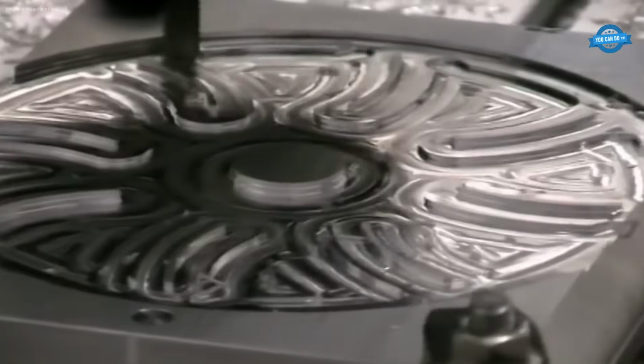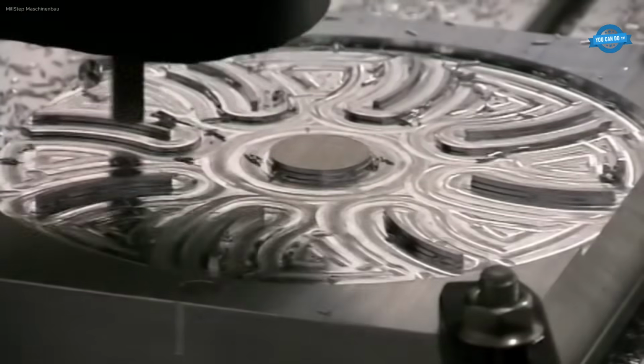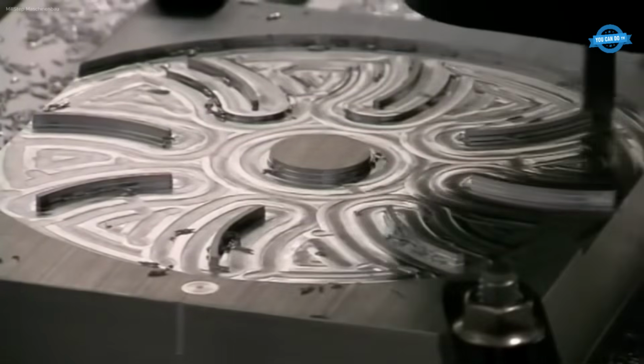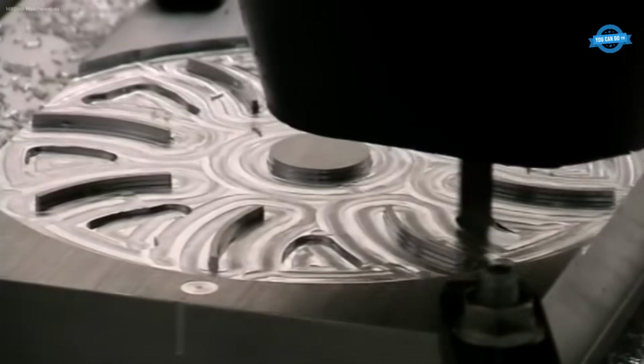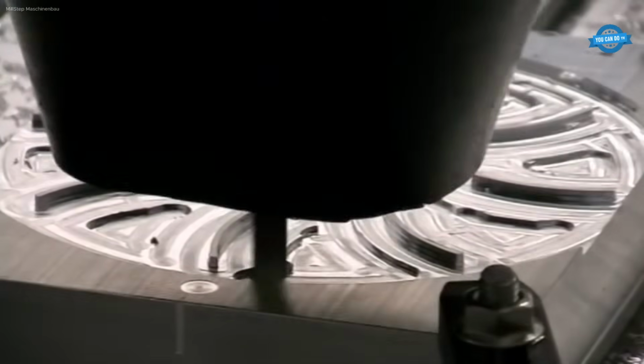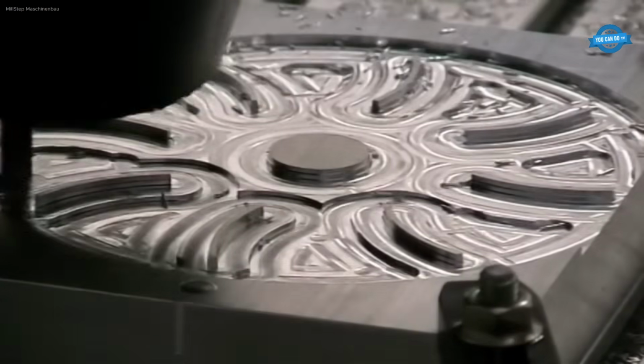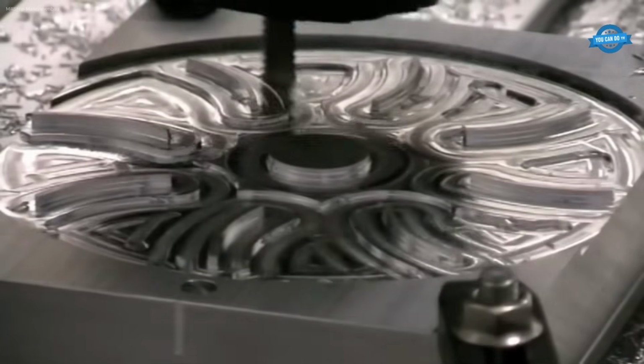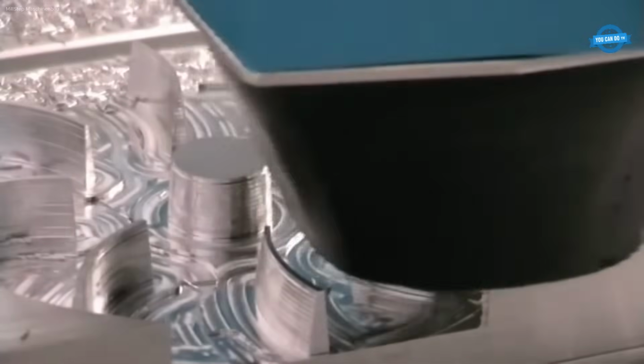Next comes spiral finishing. A 6 mm ball nose cutter executes a simultaneous 3-axis movement. With a step over of just 0.07 mm and feed rate of 35 mm per second, this stage focuses on surface quality, producing smooth, flowing contours. The transition is quiet, almost meditative, as the machine glides over the aluminum like it's tracing air.